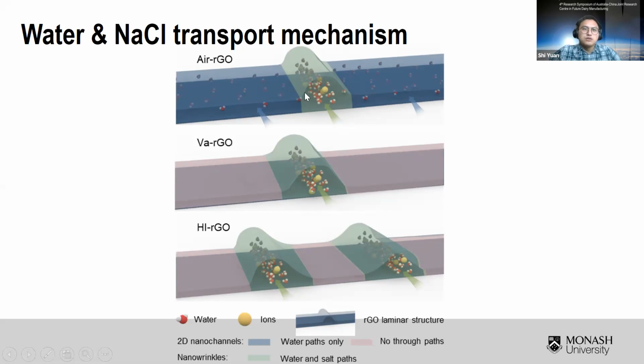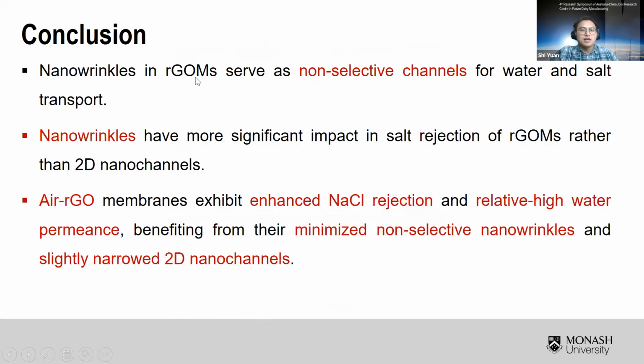When the size of 2D nanochannel is between water and the hydrated sodium, a small amount of salts will go through the nanowrinkles, and the water can transport in both regions. So the sodium chloride rejection rate is enhanced. In conclusion, nanowrinkles in RGOMs serve as a non-selective channel for water and salt transport, and nanowrinkles have more significant impact on salt rejection of RGOMs rather than the 2D nanochannels.